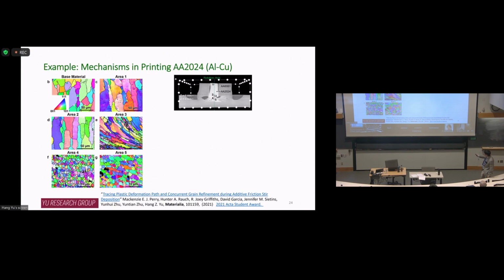This is my base material microstructure. This is area 1, which is at the top in the print head. And you see there's not much difference, right? So there's not much going on. Area 2 is still in the channel, but right before the material comes out of the channel. If you look at the microstructure, okay, a little bit is going on, but not much. Right? Area 3 is right below the channel, so the material has just come out of the channel. You see the microstructure has significant change. I got elongated and thin grains, right? And I can see a lot of gradient of the orientation angle inside the grains. I start to form subgrain structures. And areas 4 and 5, basically after that, I already have dynamic recrystallization complete. I got equiaxed and smaller grain size.